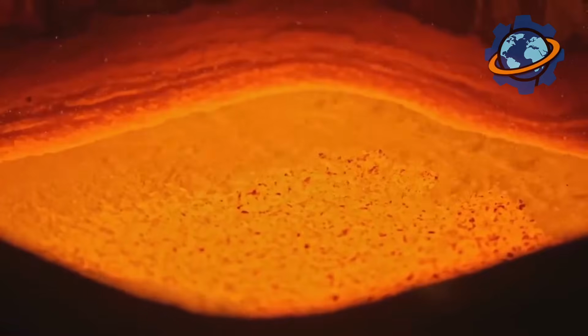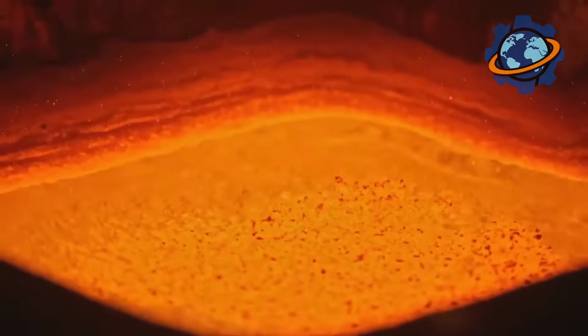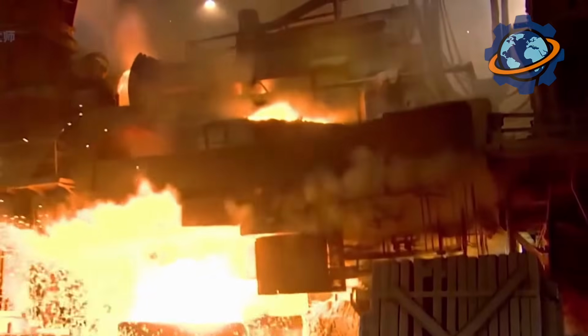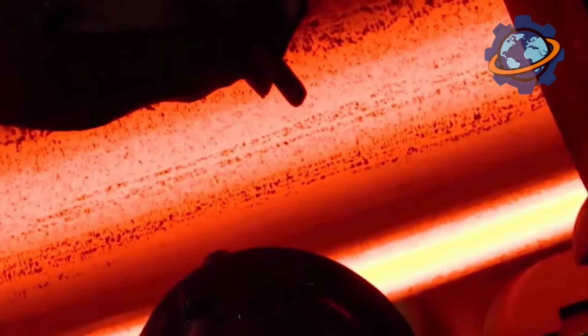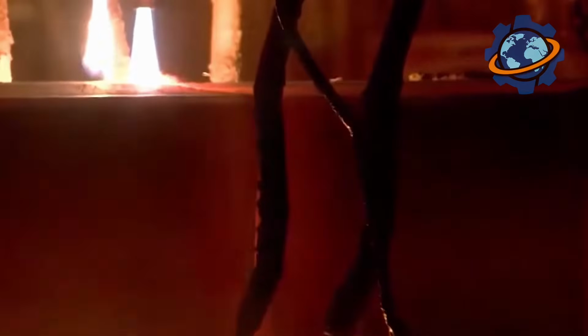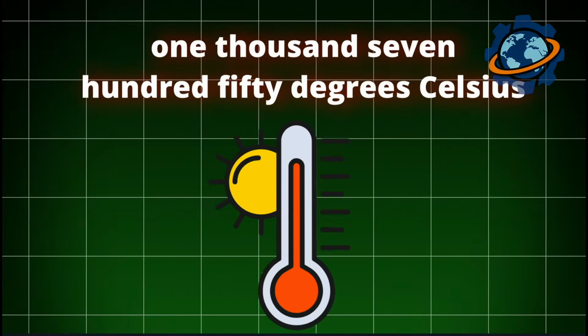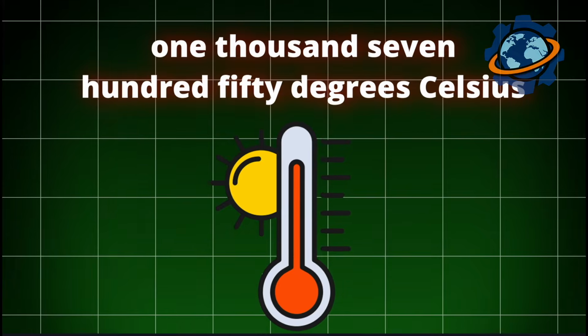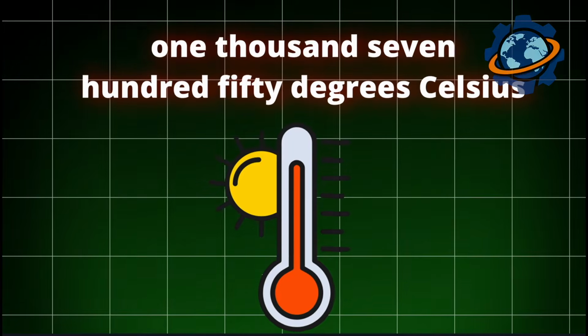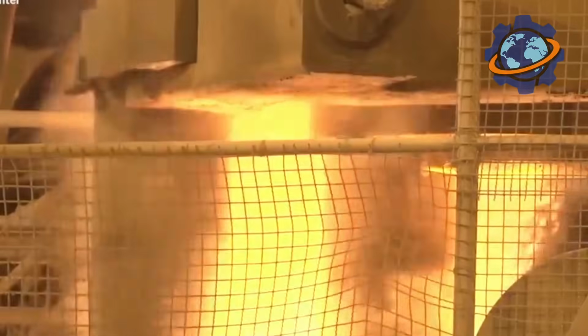The brick enters the fiery tunnel of the kiln, where a true rebirth awaits it. Slowly moving through different zones of the kiln, it is gradually heated to peak temperatures, which for chamotte brick are 1,400 to 1,500 degrees Celsius, and for high alumina types can exceed 1,750 degrees Celsius. This is not just drying, it is a deep metamorphosis.